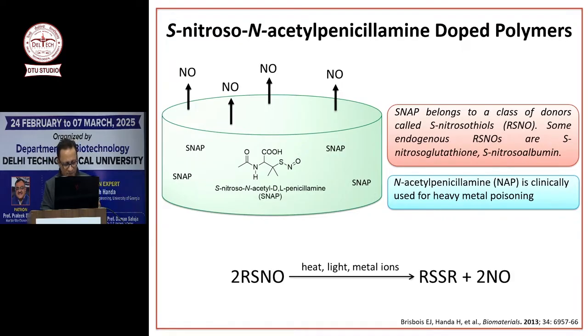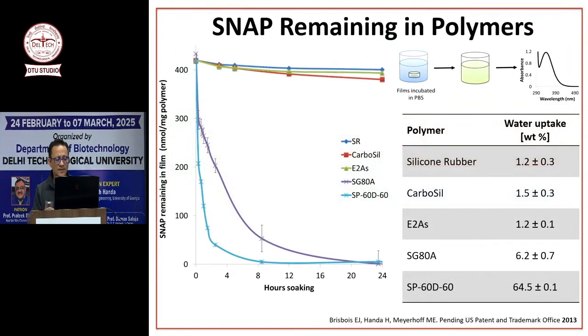Okay, so with this work, we again wanted to go to the same question, which polymer to use. So we tried a lot of different polymers with different water uptake. Silicone rubber, CarboSil is a copolymer of polyurethane and silicone rubber. E2AS is a copolymer of polyurethane and silicone rubber. SP60D60 and SG80A are polyurethanes, just two different types of polyurethanes. Now, remember one thing, the top three polymers have very low water uptake, 1%-ish. And the bottom two have very high water uptake, 6% and 60% water uptake.